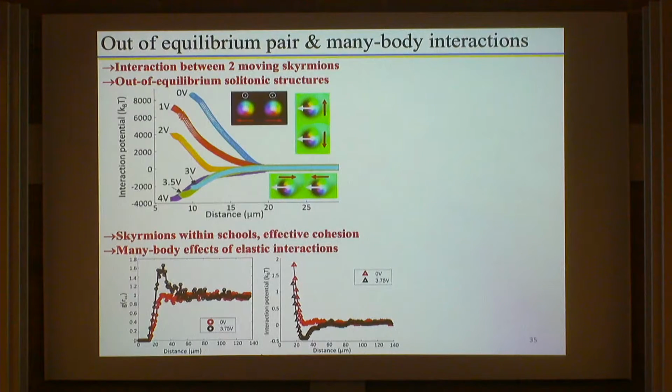So first of all, the individual skyrmions interact with each other repulsively at no applied field, right? And so you can think about them as dipoles which are perpendicular to the two-dimensional plane in which they are confined and they are repelling each other. However, as you apply external field, you are progressively tilting these dipoles to be more and more in plane, and then they start interacting attractively when they are one behind each other, and when side by side they repel each other, right? So this is giving the origin to the skyrmion chains that we discussed before.